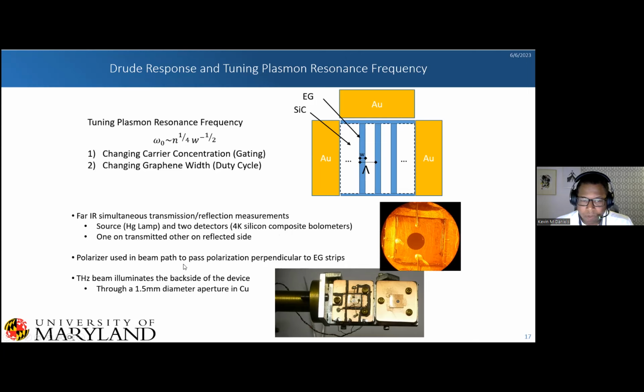And then we have a polarizer used in the beam path to pass polarization perpendicular to the graphene strips. And the THz beam is illuminated on the backside of the sample. And we have this really cool copper aperture here that we're shining through.